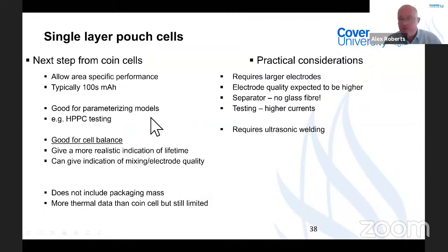So one thing just to mention here at this stage, the single layer pouch cells. I would say these are something in between the multi-layer pouch cell that I mentioned, and also the coin cells. And these are a very, very useful tool in developing cells. So what you're effectively doing is you will take one electrode of anode, you'll put a layer of separator in between, and then one layer of cathode on top. And you put this in the pouch material.